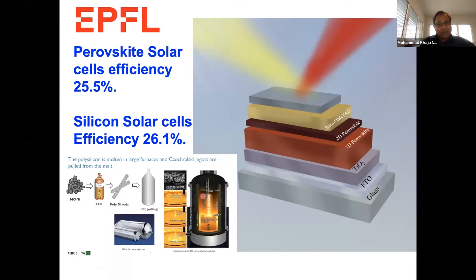Let's compare perovskite solar cell and silicon solar cell efficiencies. Perovskite solar cell efficiency of 25.5% has been certified, and silicon solar cells are at 26% — the gap is closing very soon. If you look at the energy payback time for silicon solar cells, it's going to be in years compared to a few months for perovskite solar cells. This is mostly because of the energy-intensive technology of silicon, requiring high-temperature processes. Perovskite solar cells are solution-processed, requiring temperatures in the range of 120 to 150 degrees, making them high-throughput — you can produce larger quantities to satisfy market conditions.